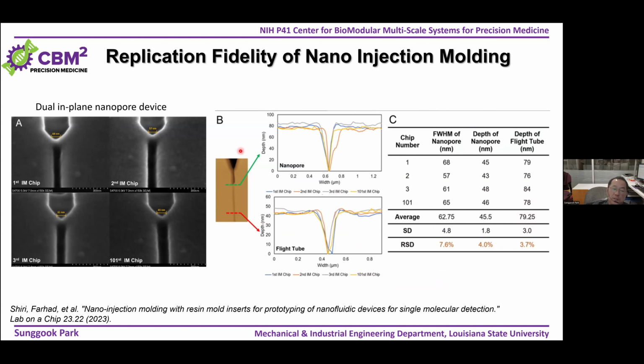One important thing is how reproducible the structures made using injection molding are. So we tried to determine replication fidelities. We made many chips, 101 chips from a single UV resin stamp, collected some samples, and analyzed the dimensions of the in-plane nanopore. What you can see here is the error. So device-to-device uniformity is really good.